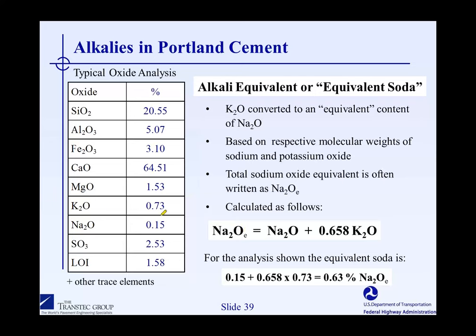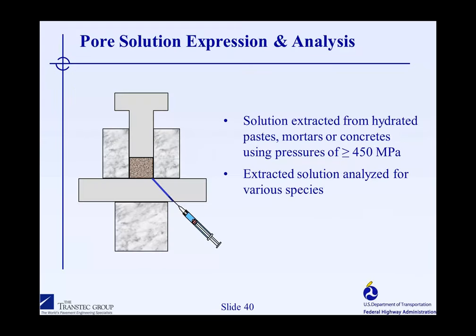If we were to look at this analysis here and try to calculate it, we take 0.15 sodium, we take our 0.73 potassium, multiply it by this 0.658, add them together, and we get a 0.63% sodium oxide equivalent, on the border of being what we know as a low alkali cement.